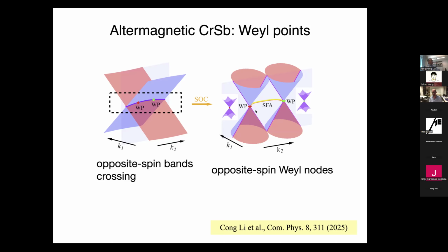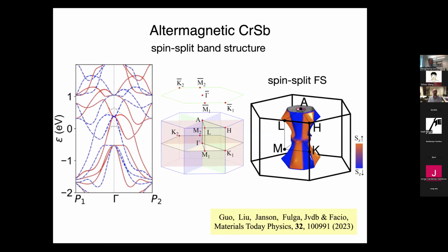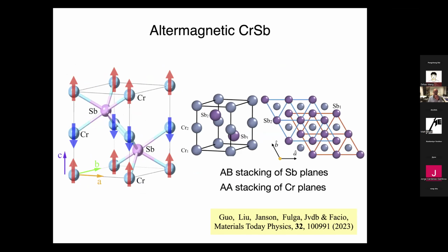Okay, that's a good question. In chromium antimonide, which is special, the spin ordering is as shown in this diagram. It's A-type, and the spin is along the Z-axis. This is a high symmetry axis, and it turns out that in this case, the anomalous Hall effect is 0.